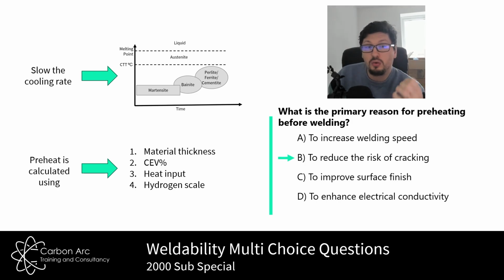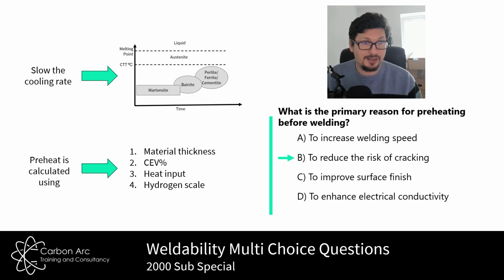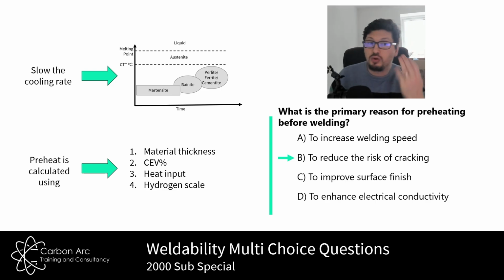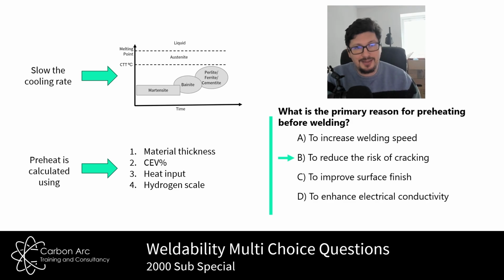Now, we use a term here called combined material thickness, which is measuring all the heat paths away from the weld itself. So if you have a butt weld, you have 2 material thicknesses, so your combined thickness is 2 times the material thickness. If you have a fillet weld, it's 3 times the material thickness. Then the heat input that you're going to put into the steel when you're welding, and then the hydrogen scale, which is a factor of the welding process, which tells you how much hydrogen is likely to be produced during that process. If you use all 4 of them, you can use a standard called EN 1011, which will then give you a preheat value, which then helps you reduce the risk of hydrogen cracking in brittle materials in general.